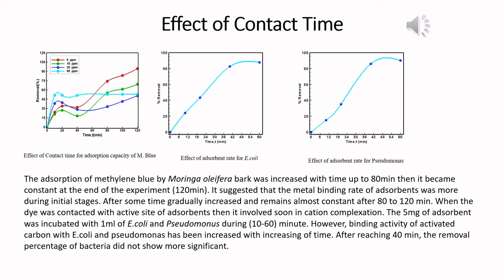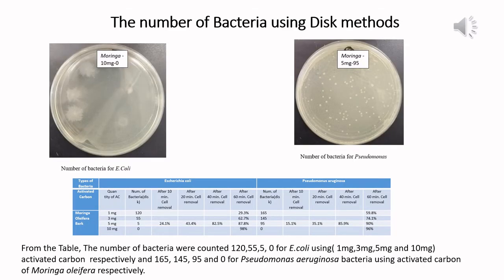The 5 milligram of adsorbent was incubated with 1 ml of E. coli and Pseudomonas during 10 to 60 minutes. However, the binding activity of activated carbon with E. coli and Pseudomonas increased with increasing time. After reaching 40 minutes, the removal percentage of bacteria did not show more significant change. The number of bacteria using this method.